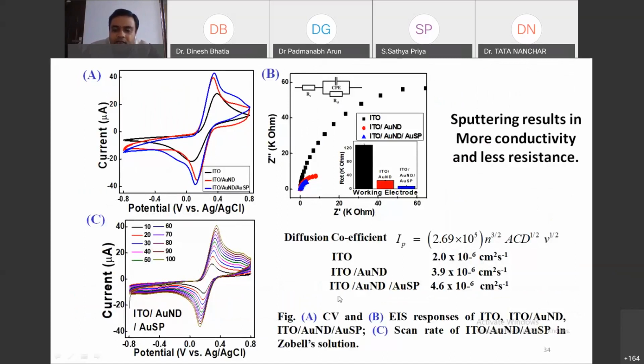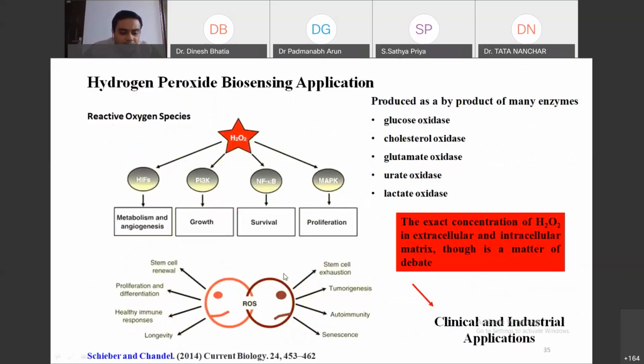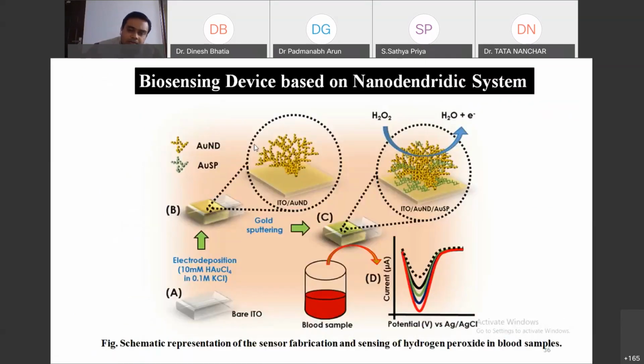So we found that at ITO and after the sputtering process, the diffusion coefficient is the highest. After the development of this 3D chip, we have employed it for the detection of hydrogen peroxide, because it has a lot of clinical and biomedical applications. This is the whole schematic representation of this particular work.